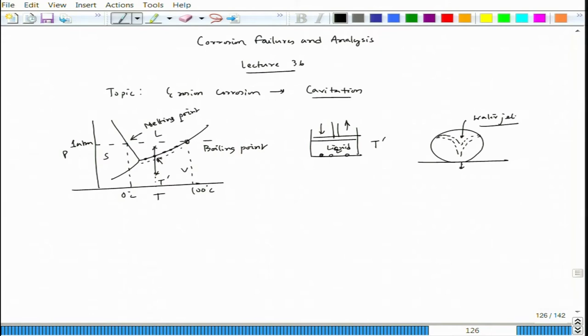So, when the bubble entirely collapses, this water jet falls on top of the metal, and gives a huge pressure, of the order of around 500 megapascal, which can deform the surface. We talked about deformation of the surface in the previous lecture, but if the surface is covered with a passivating layer or oxide layer, then because of that high pressure, the impact of that jet over the metal surface can break open the passive layer. Then it will expose the fresh material, and if it does not have any passive layer, then the base metal can deform. So, deformation can lead to extra corrosion, and then again one bubble forms because of the decrease in pressure, and the next process, increase in pressure, bubble collapse, and that process goes on.